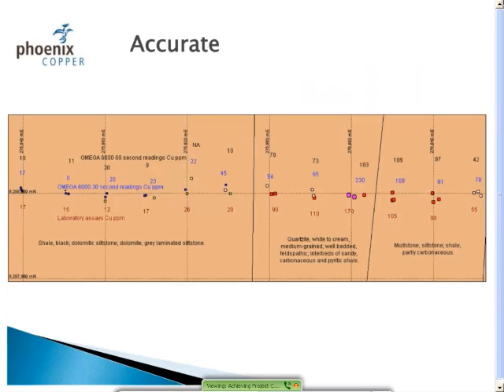This slide shows the results of an initial orientation survey by Phoenix Copper to help them establish the best methodology of testing going forward. Left to right is one soil sample grid line. In red are the laboratory results of samples collected from these locations. In blue, the XRF results of a 30-second test at that location, and in black, above that, are the results of the XRF 60-second test.